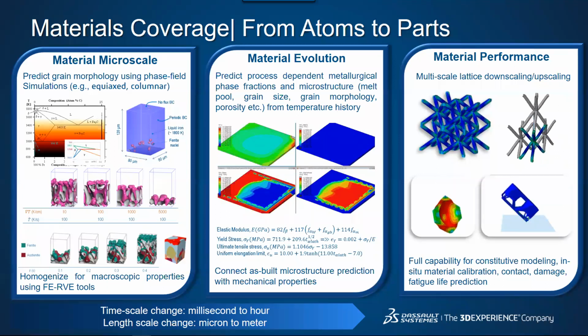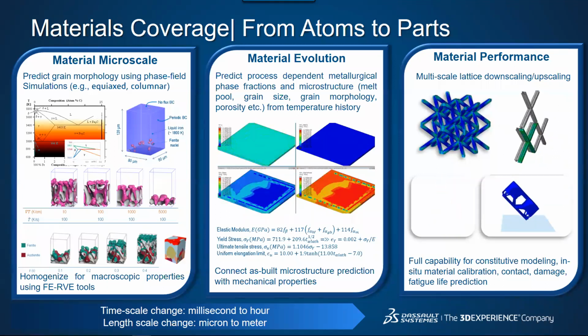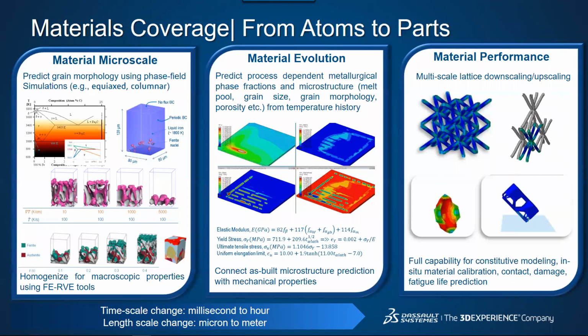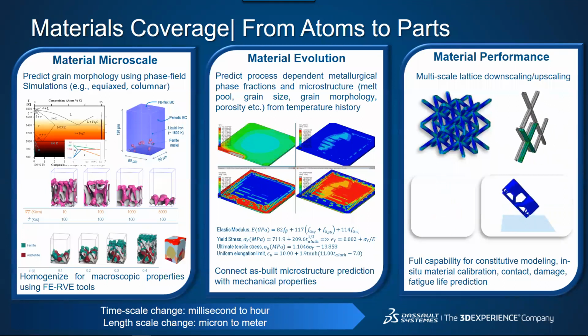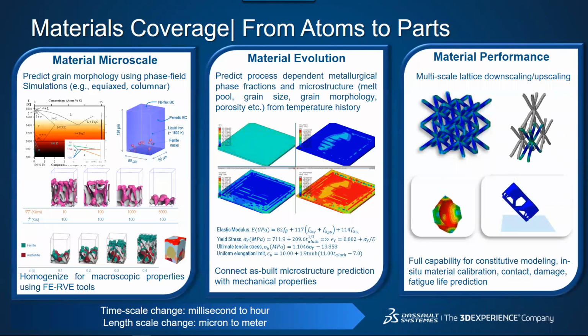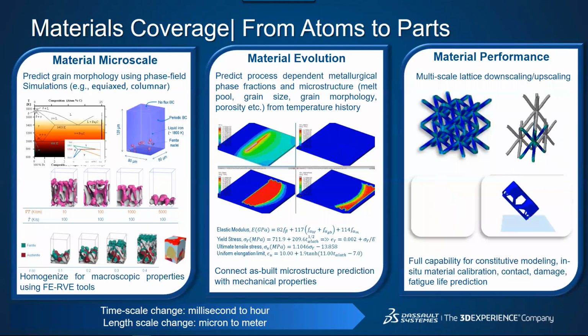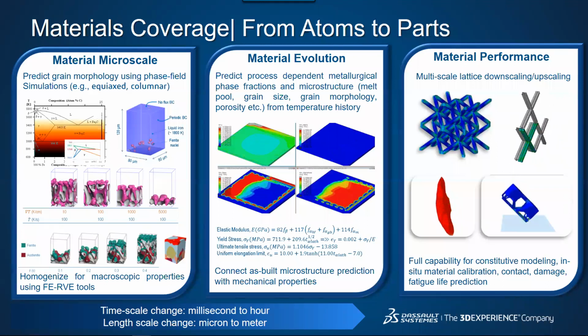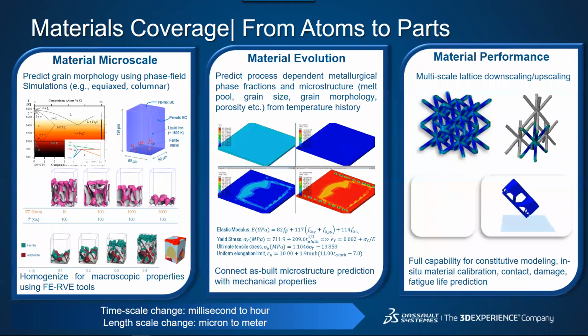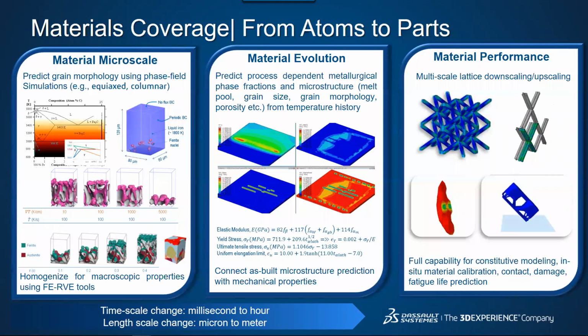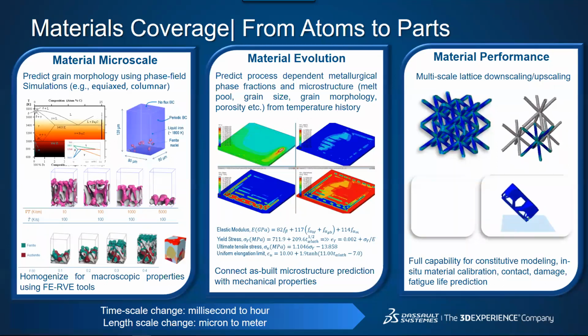If we look in the middle box, during the print, we have solutions to capture material property evolution. We can monitor the cooling rates in these thermal analyses for our build process, and by monitoring those cooling rates, we can predict the metallurgic transformations that are going to occur, which will give us phase content, grain nucleation, and porosity. Once we have these microstructure results, we can translate that to as-built macroscale material properties of the part.